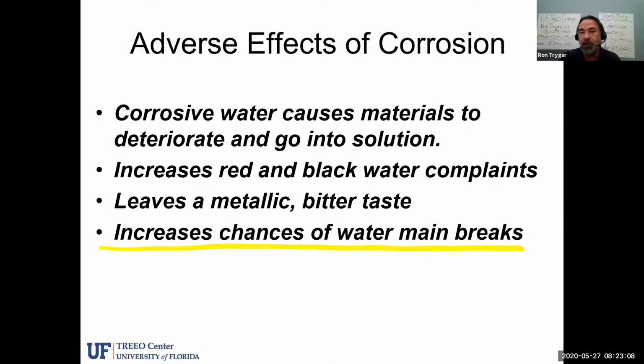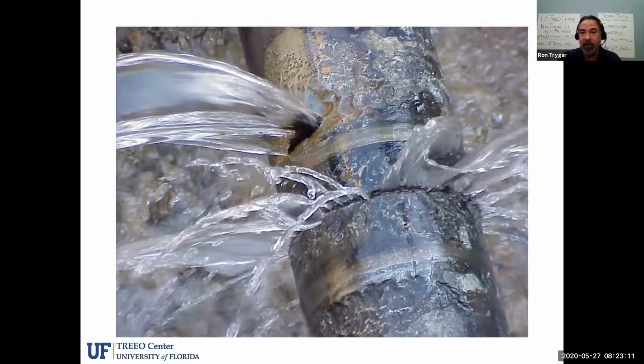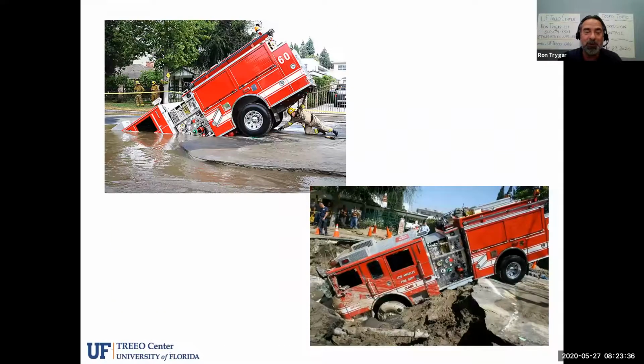So obviously you can see in this picture we have a water main that's being repaired. This was a break, and I'll point out to you here the crack or the break is right about there in the pipe, and you can see that they're already starting to make a repair. They're cutting through that pipe with a cutting tool to take out the segment that's all broken. And this is what happens when we don't pay attention to leaks. Now, you can probably go online and find all kinds of pictures of water main break and pavement damage and roadway damage.